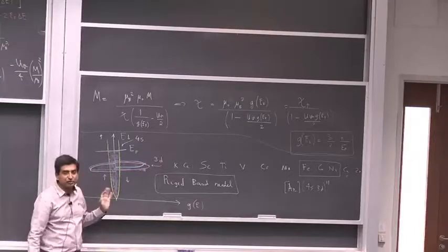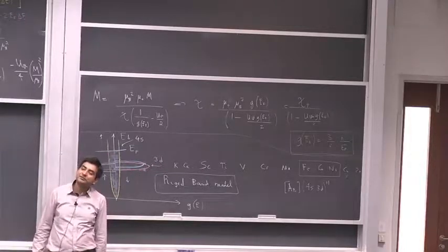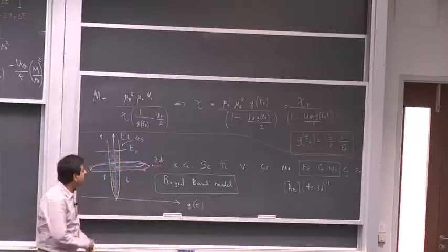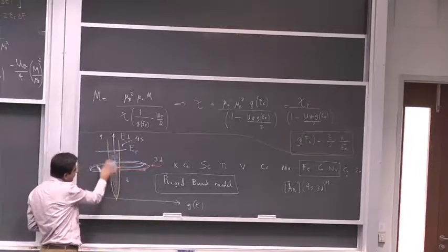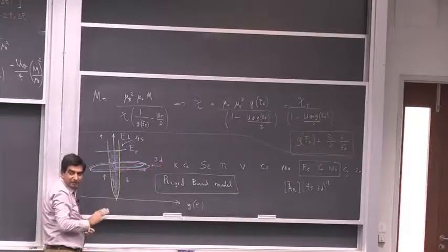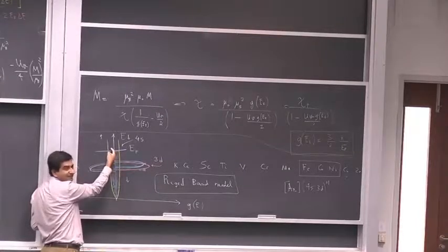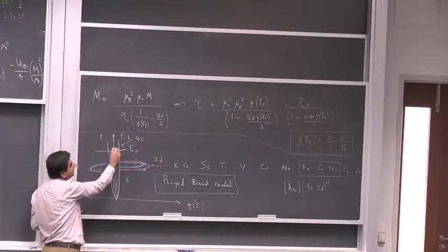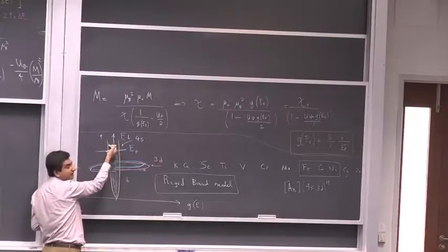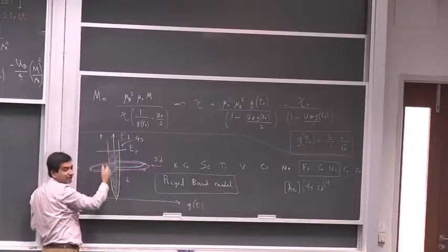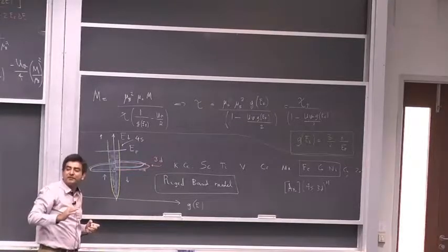So now we see that copper is not ferromagnetic because the Fermi level lies in the 4s band. For any electron here, no shifting, no reversal of spins can take place anywhere because everything is jam-packed over here. Everything is completely filled. If an electron here would like to reverse its spin and go here, since the spacing between the k levels is large, the electron will have to increase its kinetic energy by quite a bit. And that's not energetically favorable. So all the action in solid state physics takes place at the Fermi level. Remember that.